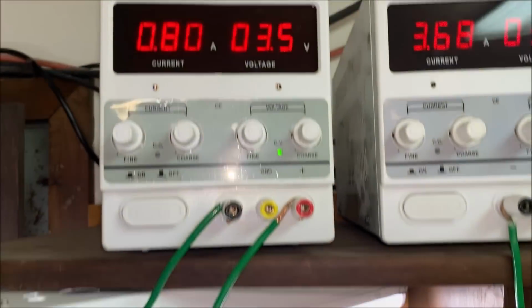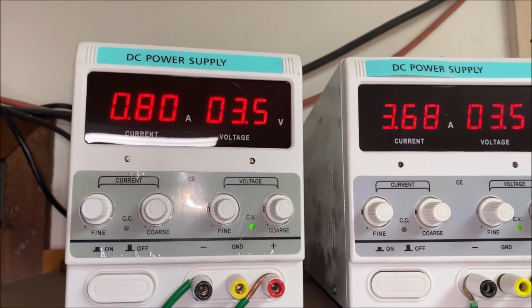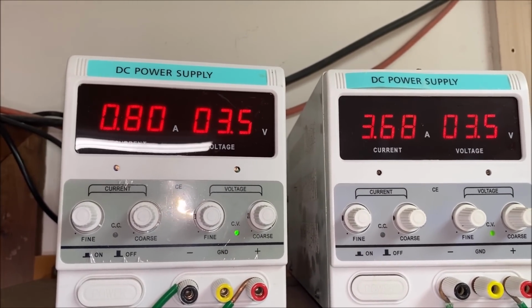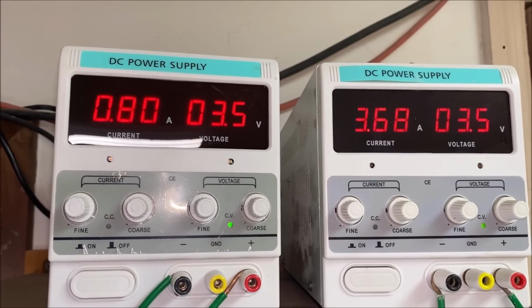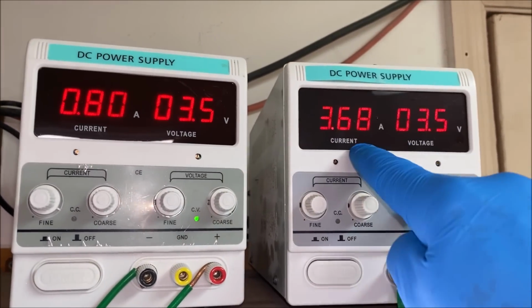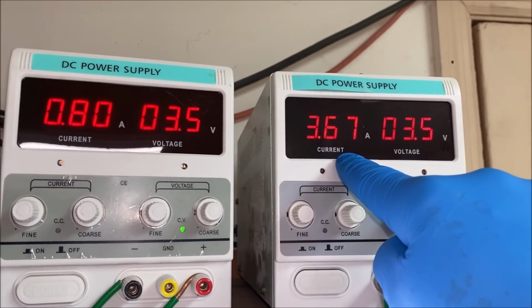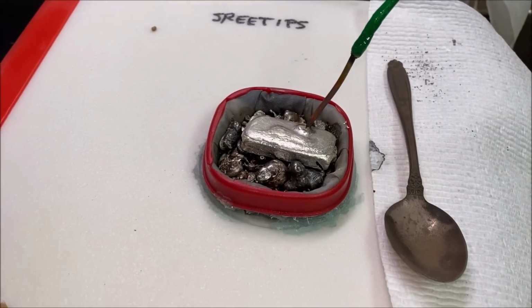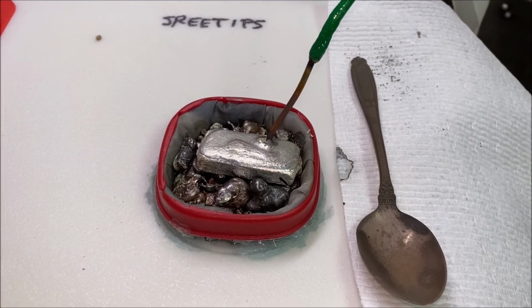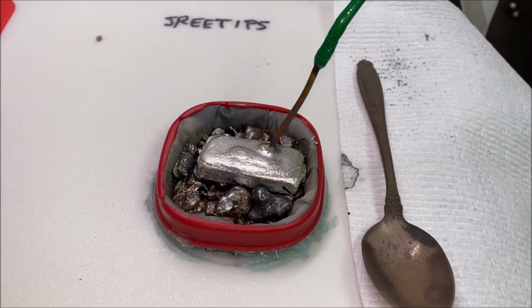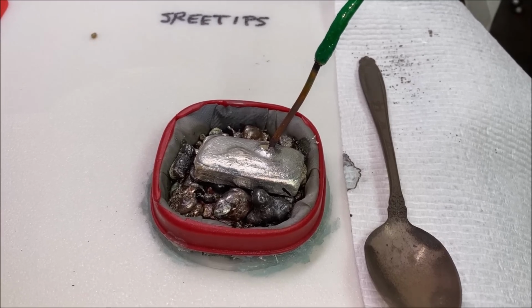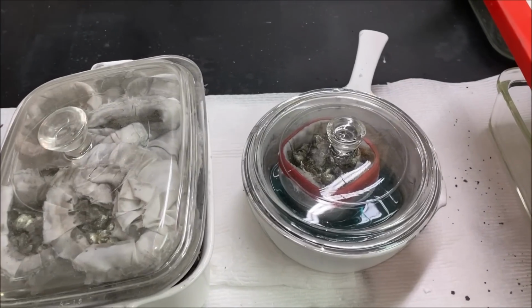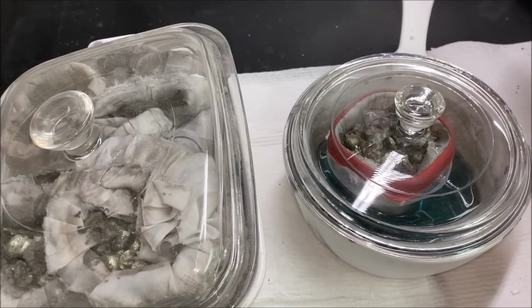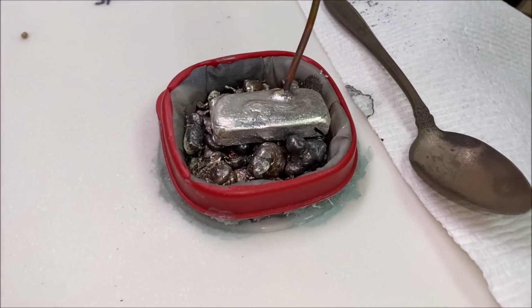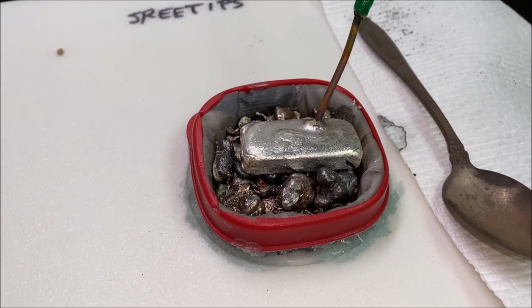And you'll see that the current flow is much lower on silver cell number 2, 0.8 amps, as opposed to 3.6 amps on silver cell number 1. And that's because the slimes in this anode filter is inhibiting the current flow through the silver cell. The traces of gold and platinum group metals that get concentrated in the anode filter basket,